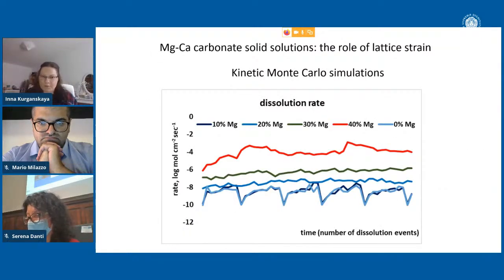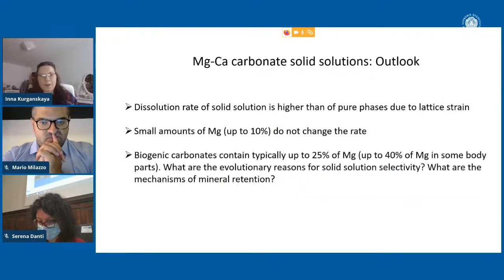So these are preliminary results for the dissolution rates. At this stage I took a small system and tried to understand how fast this mineral will dissolve if I dope it with different amounts of magnesium. The result is incredibly interesting. It showed that the material can dissolve up to 5 or 6 orders of magnitude faster than the pure material itself. But if we add a small amount of magnesium, such as 5 or 10%, the rate is not really different. So in general, we know already that these materials are very reactive due to the strain. Biogenic carbonates typically contain up to 25% of magnesium everywhere, and this is quite interesting, and even up to 40% in some parts of the body.